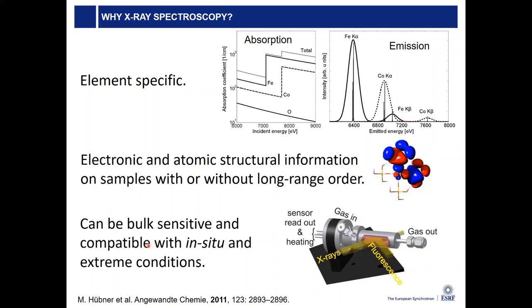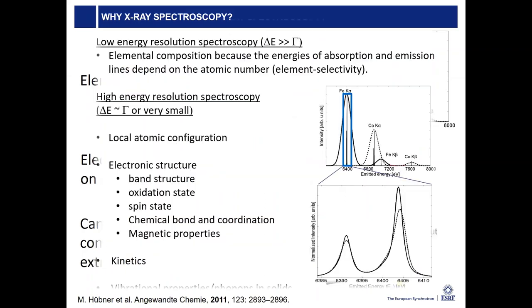If you do hard X-ray spectroscopy, but also in the soft X-ray range, this technique is bulk sensitive, especially in the hard X-ray range. And since the penetration depth is rather large for the X-rays and fluorescence coming out, you can do in situ experiments. You can put your sample inside a cell with a window in front in order to keep a certain gas environment around the sample, heat the sample, and so this can all be done. You can do high pressure experiments in diamond anvil cells because of the high penetration depth of the X-rays. So this is all important for the justification why you would like to do X-ray spectroscopy.